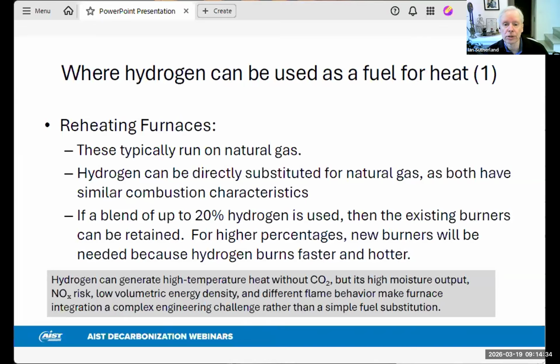Hydrogen, as I mentioned, can also be used to create thermal energy, and it can be used in reheating furnaces that typically run on natural gas. Hydrogen can be directly substituted for natural gas in these furnaces, as they both have similar combustion characteristics. Moreover, if a blend of up to 20% hydrogen is used, then the existing burners in the furnace can be retained. However, once you go beyond that and up to 100% hydrogen, new burners are needed because of the way in which hydrogen burns, faster and hotter than natural gas.